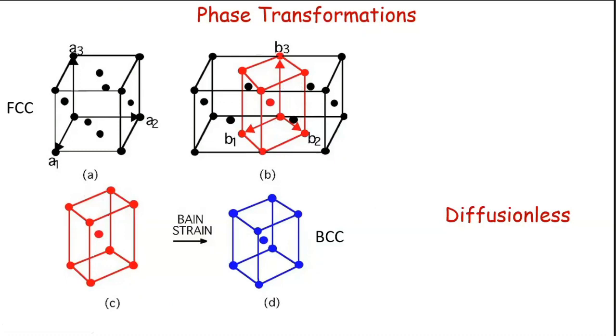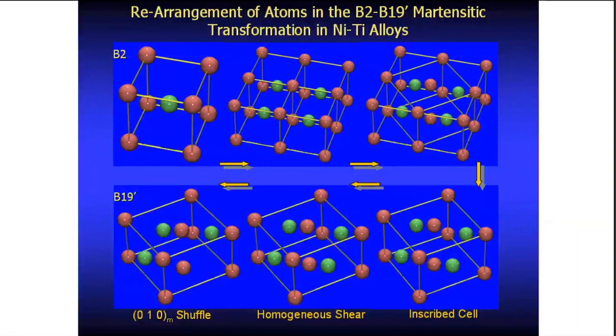So this is the diffusionless transformation that happens, and a class of this diffusionless transformation is a martensitic transformation. So the martensitic transformation occurs by shear. So what you see here is a shear. And let me see if the next slide I've actually included it. Oh, okay. So I'll just give one point before that, is that the shear itself has several components.